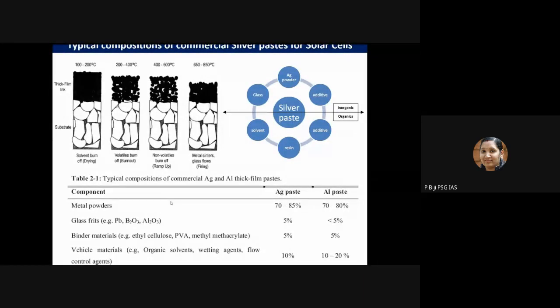If you see this table, I have listed out the kind of compositions which are used in silver and aluminum thick film paste. The metal powders will be there, that could be silver. In the case of silver paste, silver will be the major contributor, like 70 to 85 percent, and there will be some glass frits or binder materials, such as ethyl cellulose, PVA, methyl methacrylate, etc. Then there will be some carrier materials, that means a solvent is required. They are the wetting agents, and they also assist in controlling the flow.